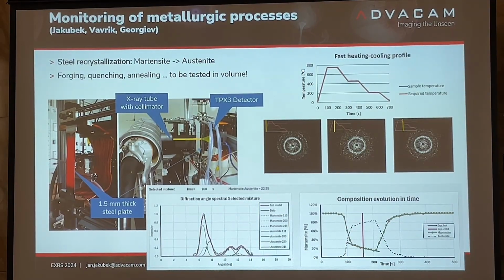So now it has dramatically changed. Now about 95% of it has already recrystallized to austenite. But we unfortunately switched off the heating too early, so it was still continuing this recrystallization. Then it started to decay back to martensite, and we ended up with martensite again. And analyzing this data, this is reality, we could find the content of martensite and austenite with precision better than 1% across the full thickness of the sample. That was amazing for us to see that the measurement was so precise. So we are already pushed to stop.